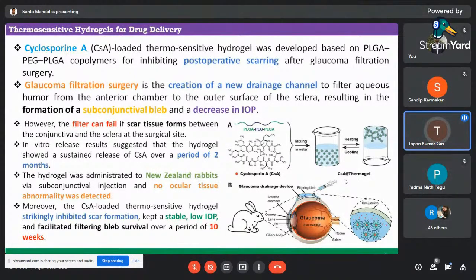Glaucoma filtration surgery is the creation of a new drainage channel to filter aqueous humor from the anterior chamber to the outer surface of the sclera, resulting in the formation of a subconjunctival bleb and a decrease in IOP. However, the filtration can fail if scar tissue forms between the conjunctiva and the sclera at the surgical site. In vitro release results suggested that the hydrogel showed a sustained release of cyclosporin A over a period of 2 months. The hydrogel was administered to New Zealand rabbits via subconjunctival injection, and no ocular tissue abnormality was detected.